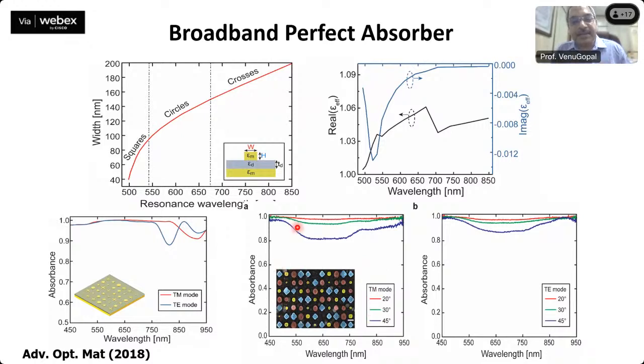Right. When we look at the reflection, we showed that we can get up to 99.86% suppression of reflection, and there's zero transmission, and suppression of reflection leads to 99.86% absorption in a thin 10 nanometer silicon layer.